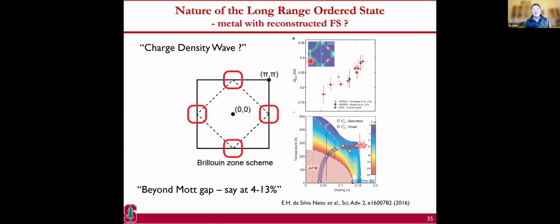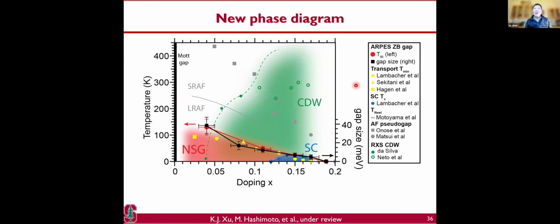However, if you look at the charge density wave, as you increase the doping, the charge density wave goes to higher gap and higher temperature, even though they're using the same piece of Fermi surface. So here's the gap. The red and the black are the data of the antinodal gap. You can see it decreases and smoothly evolves into the d-wave superconducting gap, while the charge density wave shows up at higher temperature and with non-monotonic behavior. So it cannot be the charge density wave.